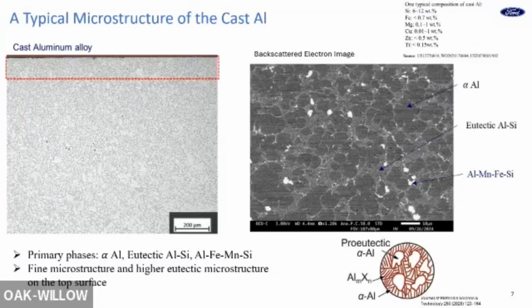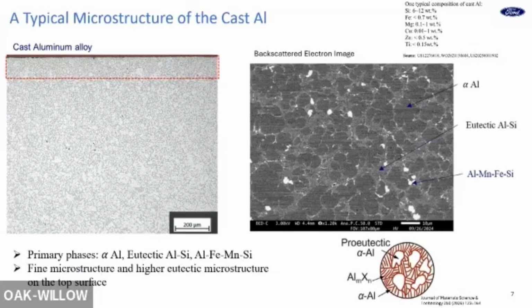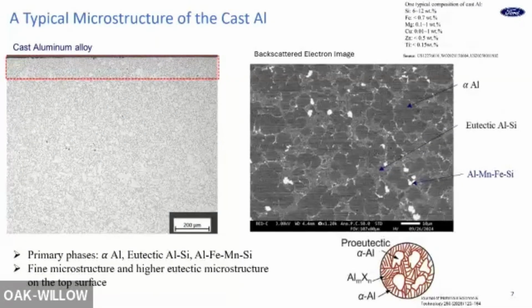But I also want to mention there are some differences between the top surface and the center, because during the solidification, the cooling rate on the surface is much higher, so you may get a fine microstructure and smaller grains. Another interesting thing you might see is the darkness. So the top surface is darker than the center. We care about the top surface because it's the top surface that reacts with the surface treatment chemicals, which can then affect the subsequent coating or performance.